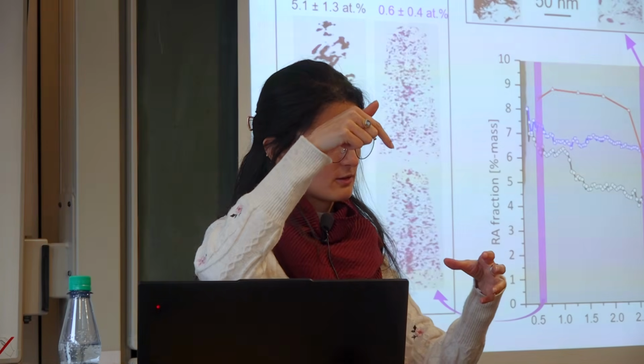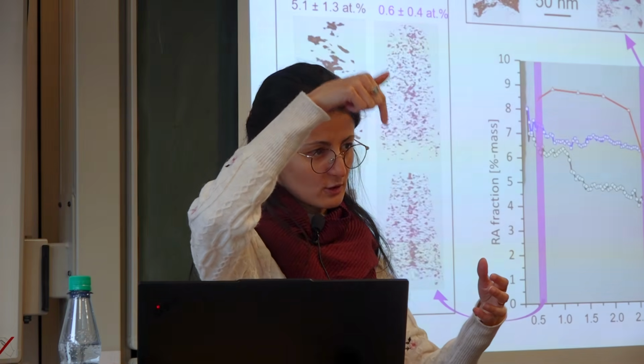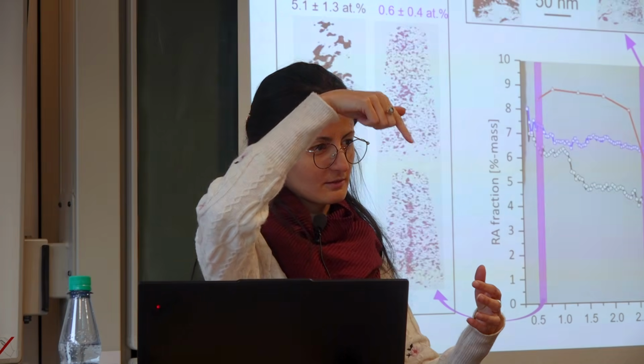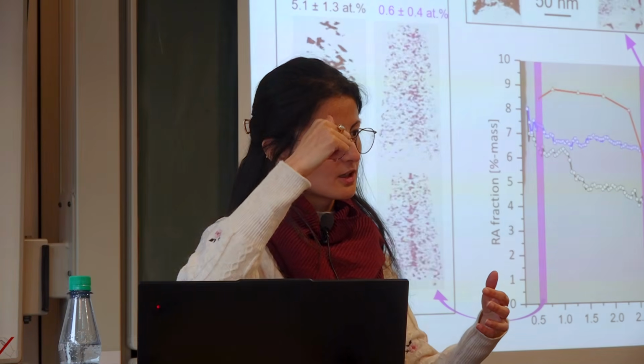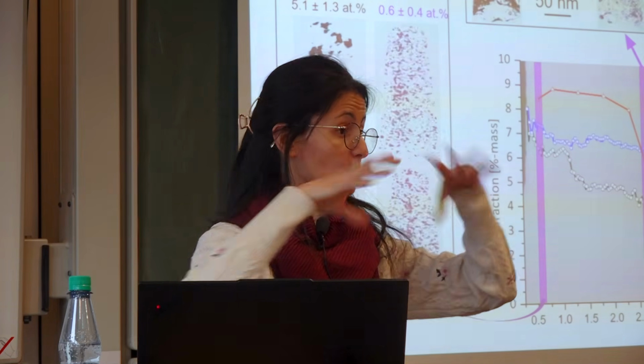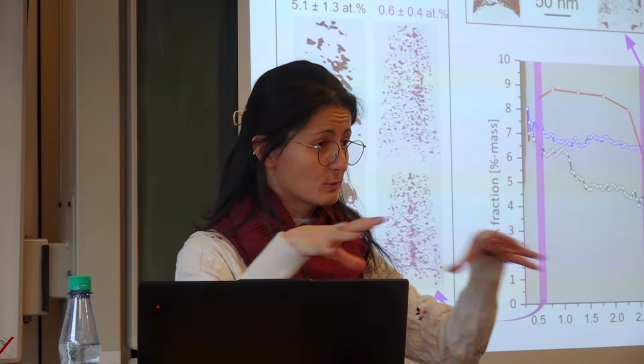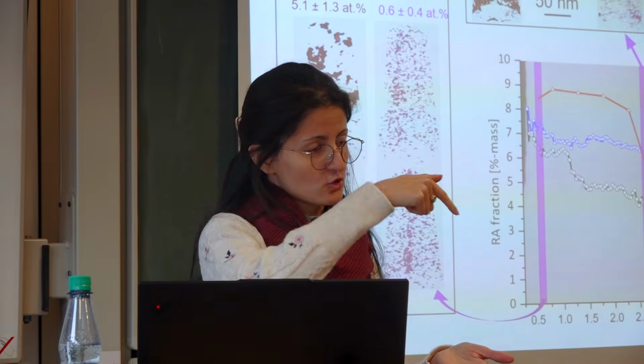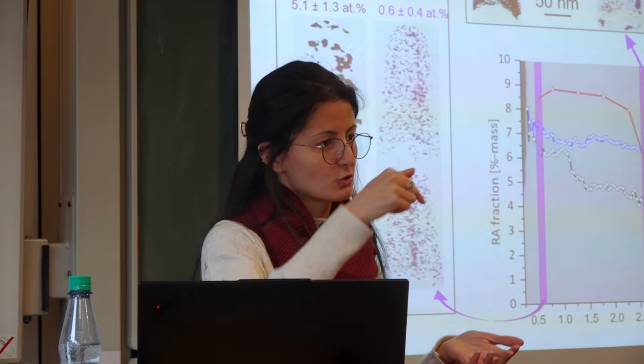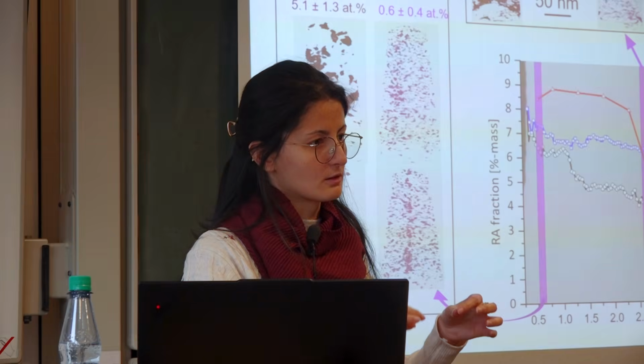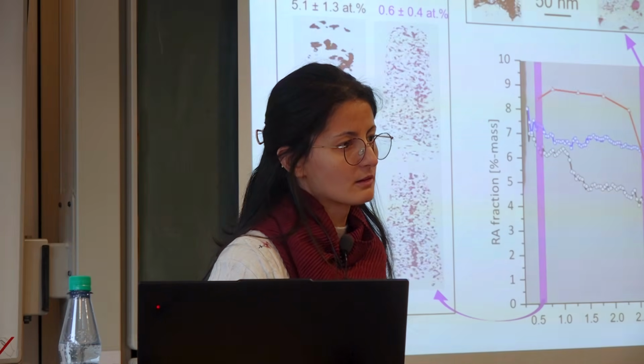And then with the ion beam itself, we mill all around. We sputter the material as a circle all around, so that we will get a very thin apex and a very thin